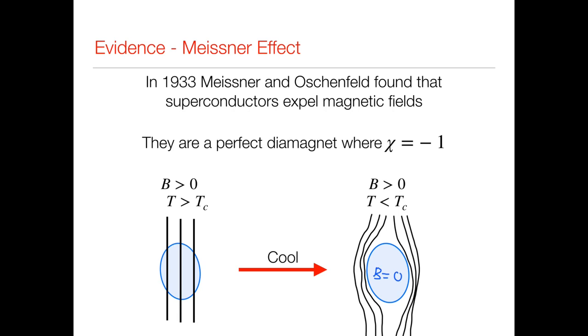That's actually probably one of the more commonly known properties of superconductors, because of course it leads to the idea of things like maglev trains. Pieces of superconductor will float above a magnet because they're trying to get out of the magnetic field to lower their energy. Okay, and I showed you a photo of pyrolytic graphite. Remember, the susceptibility of that was of the order of -1 times 10 to the -5. So the effect here is significantly stronger.